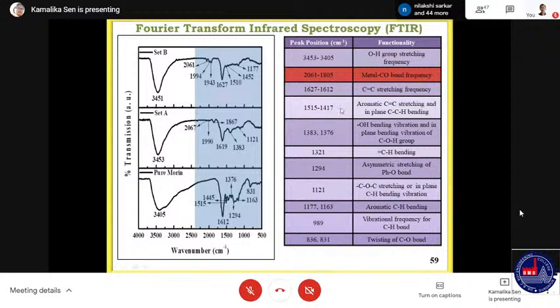And from the FTIR spectrum, here it is complex formation, unlike the palladium quantum dot one, and we can see that there is metal carbonyl bond formation. See here in this pure morin, 2060 to 1805 centimeter inverse. There it is. Here there is generation of new peaks. That means there is metal carbonyl bond formation in both set A and set B, and in set B the peak intensities are higher than in set A. That means more of the carbonyl group is involved in the bond formation with the metal.